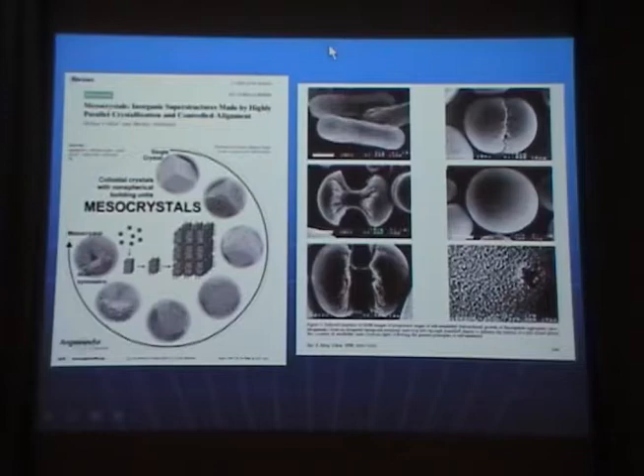Okay. So now the question arises, how come that you can take a single crystal, which is hexagonal structure, and then mix it in some sort of solution, and overall get a spherical crystal forming? The other question you could ask, even if that would be somehow possible, which I showed it could be, how come it's still birefringent? What birefringent means is that you have a predominant optic axis along which you have your ordinary and extraordinary refractive index. So those indices have to be maintained in this micron-sized crystal, which is pretty surprising, isn't it? Okay. So how come that those crystals which form and can be actually spherical can still be birefringent?